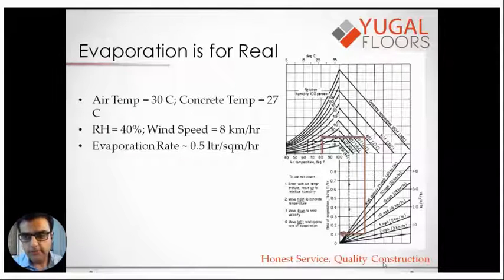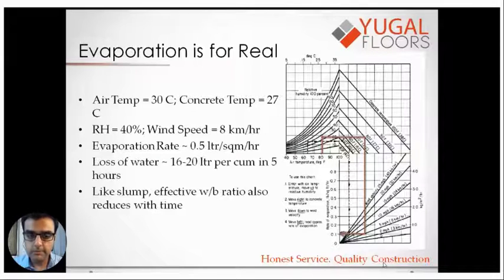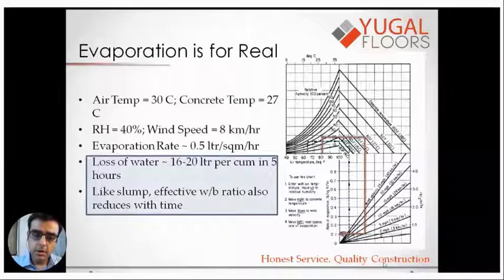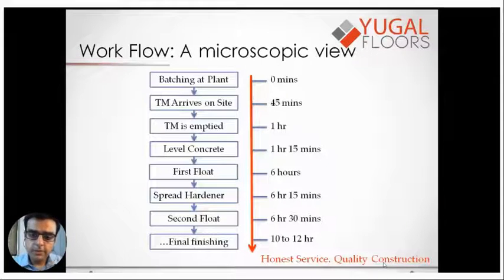And I would like to remind you that it takes at least about 5 hours for the finishing to start, and give and take an hour for the transit time. So we're looking at a 5 or 6 hour time period where there's evaporation happening in the concrete. That is the least I'm talking about. So what it means is there's a loss of water of 16 to 20 liters per cubic meter in a period of 5 hours. So the message here is, like slump, the effective water binder ratio also reduces with time. The water binder ratio is not a fixed number, it is dynamic. All right, so I have thrown three variables at you: batching speed, variation in arrival of trucks on site, and evaporation.